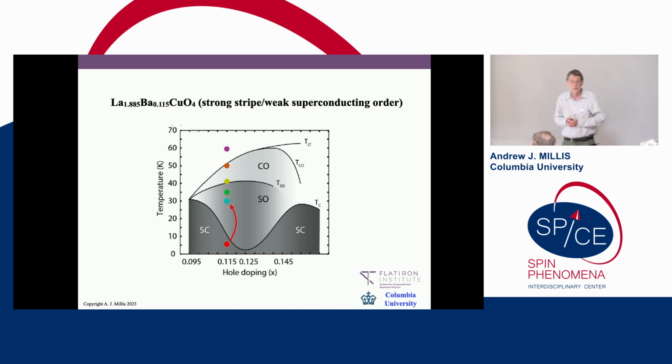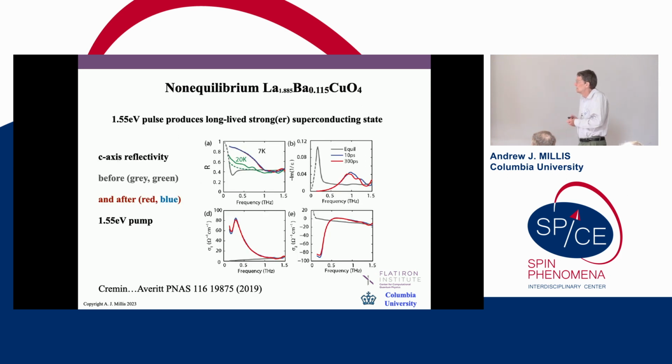and superconductivity comes back. Okay, so what they did was do an ultrafast experiment where they pumped the material above the band gap at the usual 1.5 eV, thereby raising the electronic temperature well above the superconducting transition temperature, and then seeing what happens. Okay. And so what happens is as follows. All right. Here are the measurements.